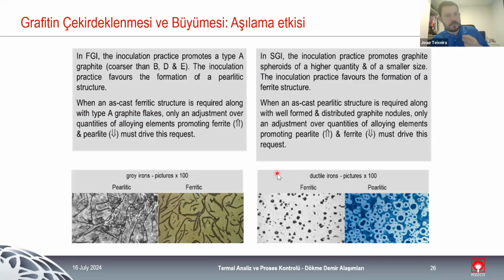And in here is just for us to discuss a little bit the differences when we are dealing with gray and with nodular. The principle is the same, solidification inoculation process. The principle is exactly the same, but the end game is a little bit different. So for gray production, we are not going to add any magnesium to the melt. So there is no change in the type of graphite that we have at the beginning and at the end. And the main objective of inoculation for gray cast iron is to promote the solidification of type A graphite. It is the best one to improve the mechanical properties.